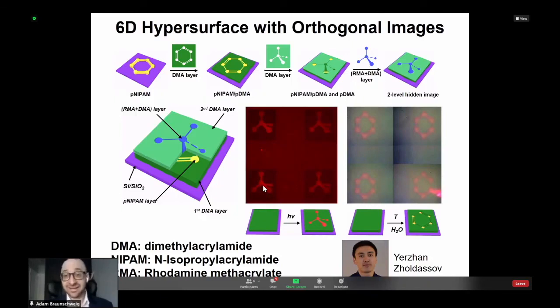If instead you take the surface and you heat it without any fluorescent light, you get these benzene rings. So here we have a surface with 2 different hidden images that appear, one if you shine fluorescent light on it, another if you heat it. And the only way we're able to achieve this is a result of being able to fully explore 400 different printing parameters so that we can control the heights relative to each other very precisely.